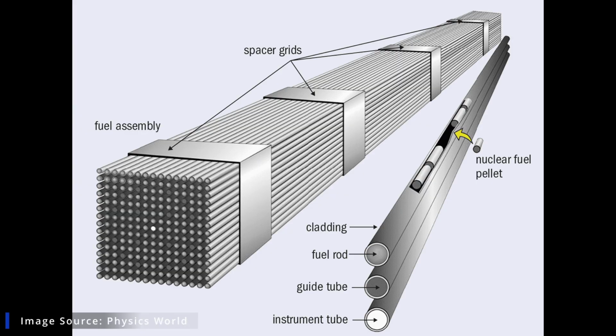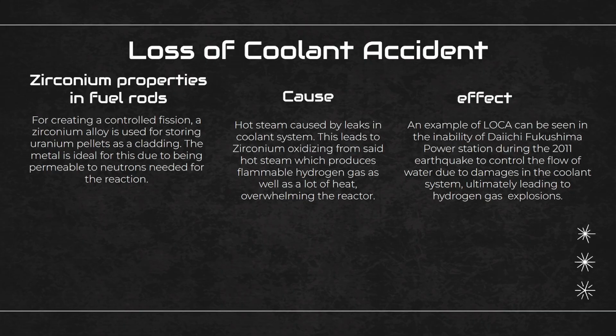For creating a controlled fission, a zirconium alloy is used as a cladding for storing uranium pellets. The metal is ideal for this due to being permeable to neutrons needed for the reaction. In a loss of coolant accident, hot steam caused by leaks in the coolant system oxidizes the zirconium cladding, which produces flammable hydrogen gas as well as a lot of heat, which can overwhelm the reactor.